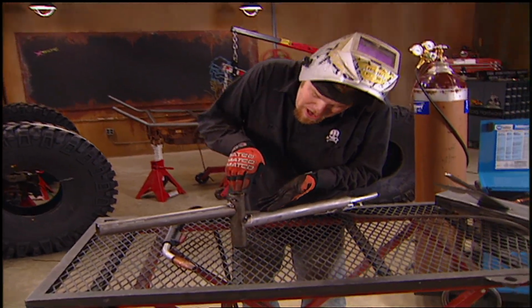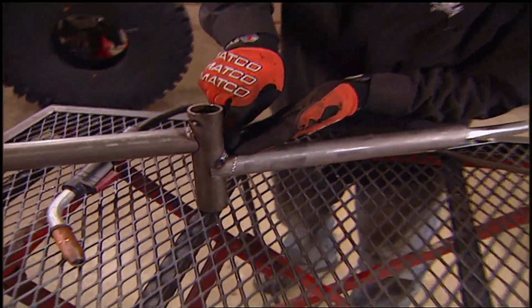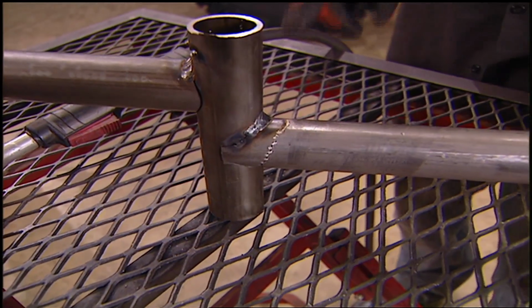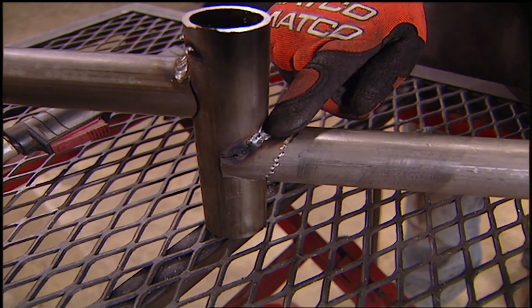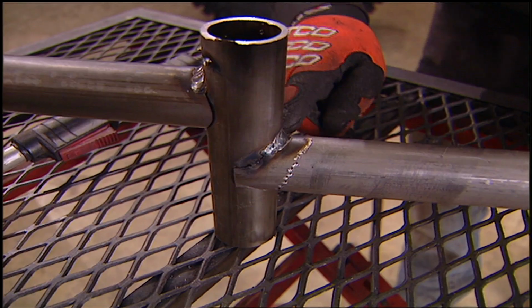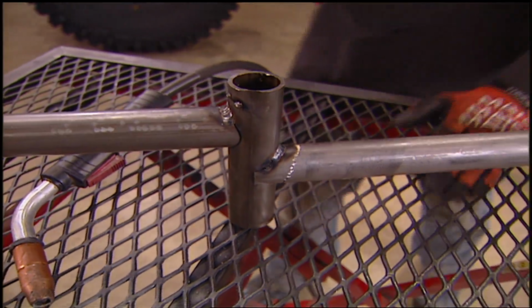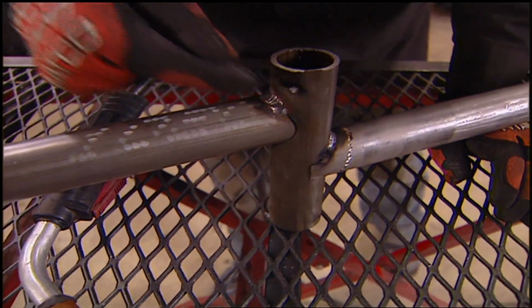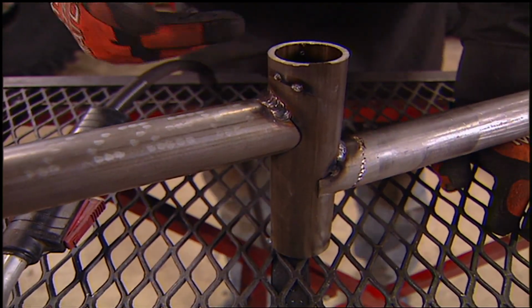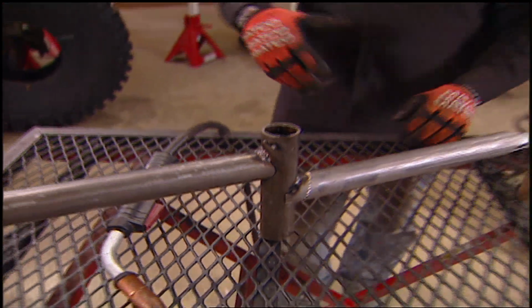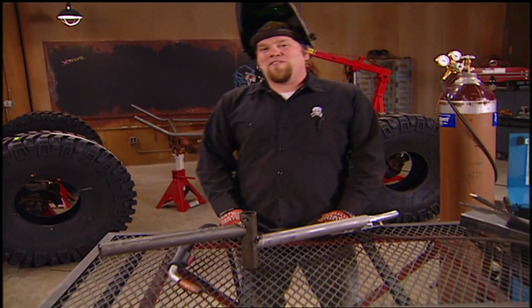When you're welding steel together, you're actually melting it together to create a bond in one joint. When you run a bead, you know that you have a uniform heat effect zone all the way across that bead. Whereas when you stitch weld, every time you start and stop, the metal can cool down, creating a series of cold joints. Now, is it weaker? You really don't know until it breaks.